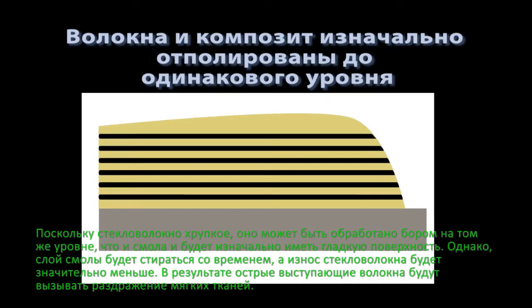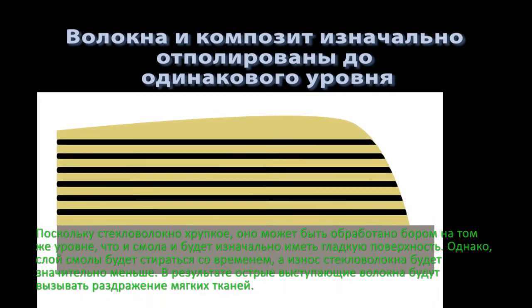Since Ribbond's fibers are so tough, they cannot be cut to the same level as the composite with a burr and will therefore feel fuzzy if polished. Being brittle, glass fibers can be cut with a burr to the same level as the resin and will initially feel smooth. However, as the resin wears away over time, the glass fibers will not wear at the same rate. This will result in sharp protruding fibers that will cause irritation to the soft tissue. Thus, in the long term, neither glass fibers nor polyethylene fibers should be polished.